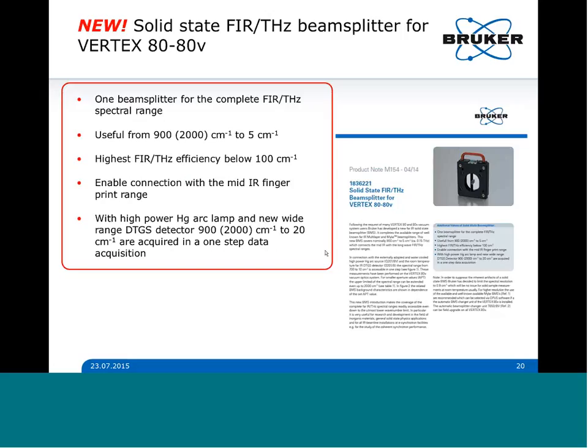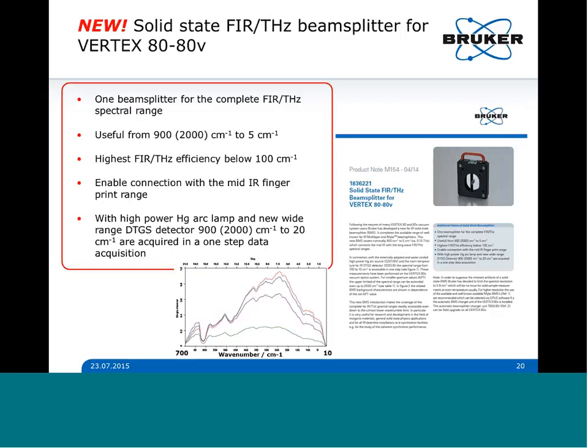And if you use a high power mercury lamp and the new wide range DTGS detector, you can cover the complete range from 900 down to 20 wave number with only one single data acquisition. And here you see a small example measured with VERTEX 80 and this solid-state beam splitter, the spectrum showing 700 to 10 wave number. This is the single channel measured using different aperture size.